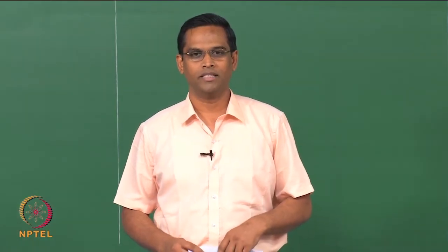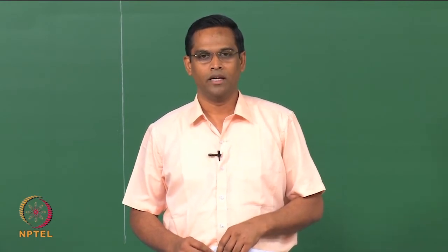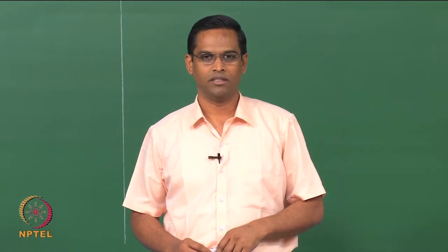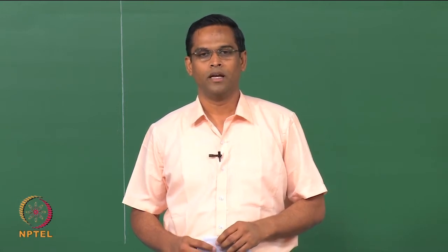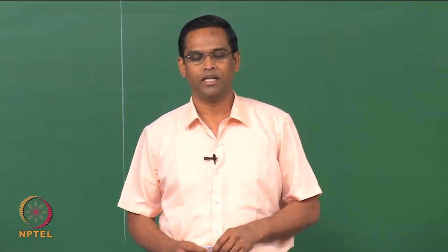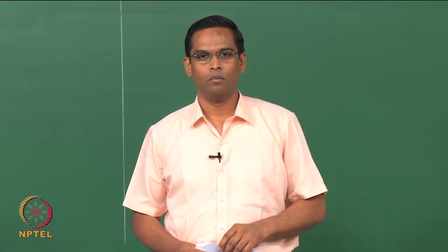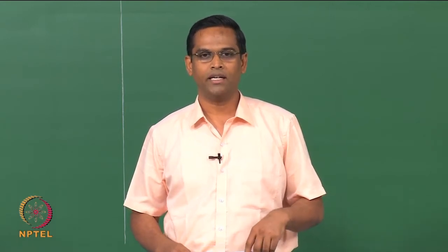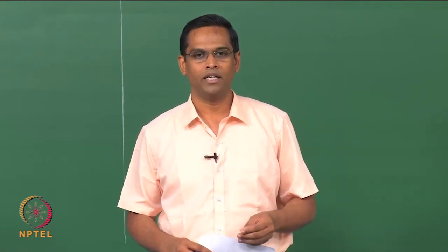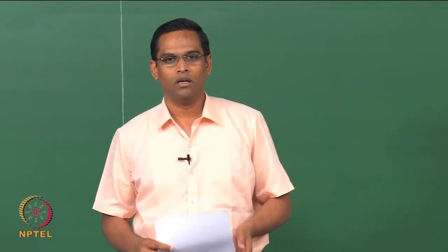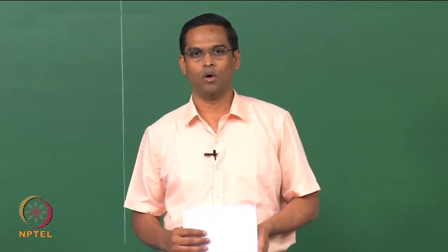In the last class, we discussed the X-ray diffraction intensity and the factors which influence it and its consequences. One of the factors we talked about is two kinds of intensity, that is I max, the maximum intensity, as well as the integrated intensity. Most of the time we are interested in the integrated intensity, and we try to interpret it to arrive at the possible crystal structure determination, or to estimate the residual stress or the crystal orientation and so on.